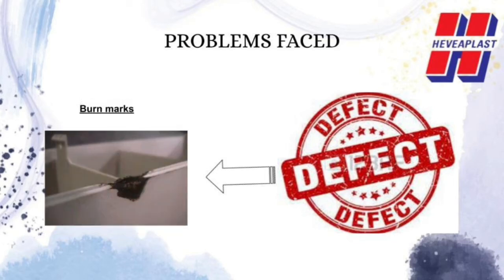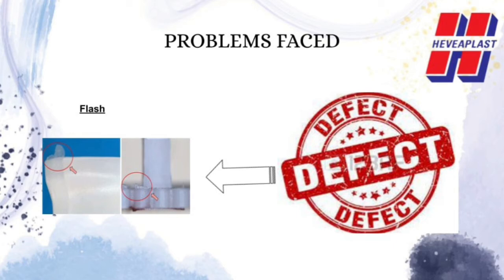The third one is burn marks. Burn marks are discolorations, usually rust colored, that appear on the surface of injection molded prototypes. Burn marks are caused either by the degradation of the plastic material due to excessive heating or by injection speeds that are too fast. Burn marks can also be caused by the overheating of trapped air, which etches the surface of the molded part. The next one is flash. Flash is a molding defect that occurs when some molten plastic escapes from the mold cavity.